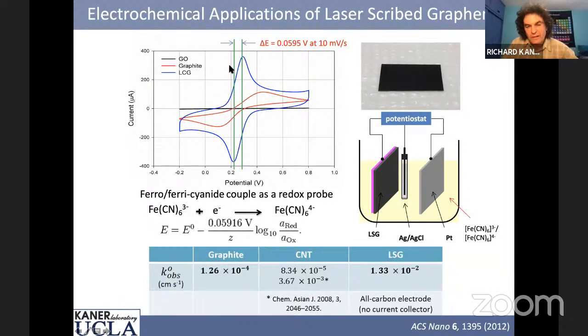And from this, you can calculate the speed of moving charge. And in laser scribe graphene, we can move charge at 10 to the minus 2 centimeters per second. If you look at graphite, it's 10 to the minus 4 centimeters per second. So what's interesting is once you make this laser scribe graphene, it's 100 times faster than graphite. And so that suggests that a good use would be energy storage, because as we know, essentially all lithium-ion batteries use graphite as one of the electrodes, and many other batteries use graphite. It's a standard electrode material. Yet now we have material that's 100 times faster.